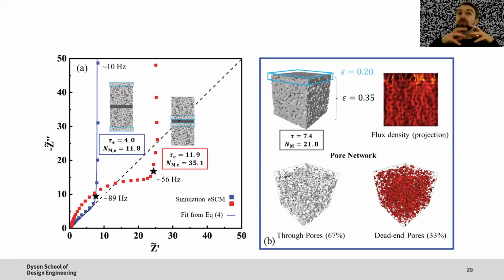So to skip to a more realistic example, and one that comes up in papers quite a lot, what happens if you've got a slightly less porous region in your porous microstructure? And this is just a dropped spheres type microstructure, right? A bunch of spheres artificially rammed together. As you would hopefully suspect, the normal tortuosity factor, the diffusive tortuosity factor, cannot tell which direction you're going. I.e., it doesn't matter whether the dense bit is near the top or near the bottom, it gives you the same number, because it's saying how easy is it to get all the way through the microstructure.